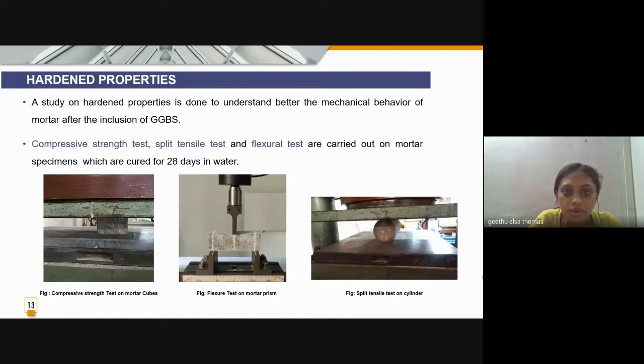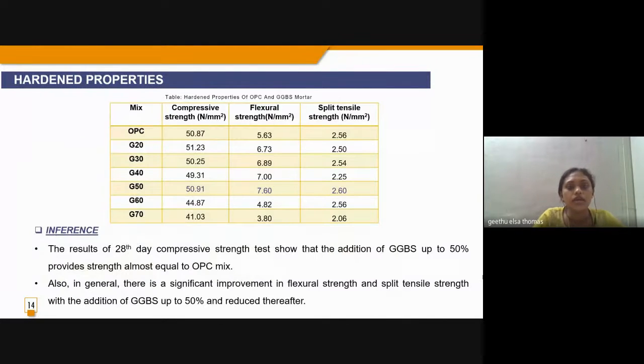Then a study on hardened properties is done to better understand the mechanical behavior of mortar after the inclusion of GGBS. Compressive strength tests, split tensile strength, and flexural tests are carried out on mortar, which is cured for 28 days in water. The results are tabulated, and it is observed that the 28-day compressive strength test shows that addition of GGBS up to 50% provides strength almost equal to OPC mix. Also, in general, there is a significant improvement in the flexural strength and split tensile strength with the addition of GGBS up to 50% and reduces thereafter.